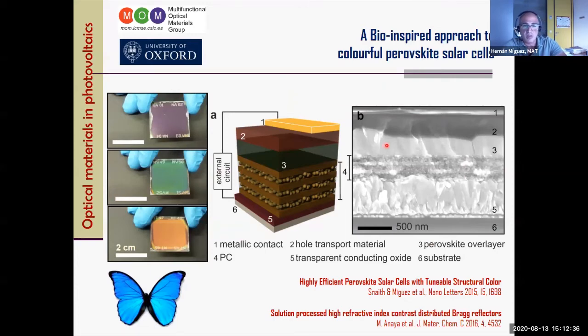nanostructured photonic electrodes, in which instead of having just titanium oxide, we have titanium oxide and silicon oxide arranged in a multi-layer, and this multi-layer is capable of changing the color of the cell. There's a certain sacrifice in the efficiency, but it is still higher than in most other emerging photovoltaics, and you can control the color very efficiently.